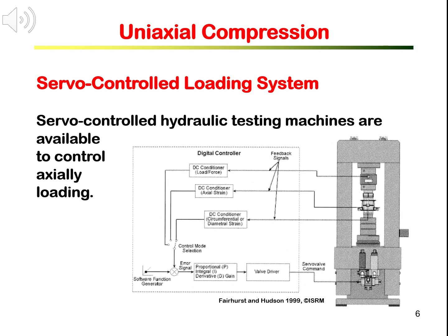The feedback signal will be the axial strain measurement. Axial strain measurements are fed to the control system by comparing the current value of the strain and the prescribed desired value of the strain. Then an order is sent to the servo valve to apply the loading to the next level of strain. Servo control systems with a high loop closure rate of at least 1 kHz in real time are recommended for rock testing.